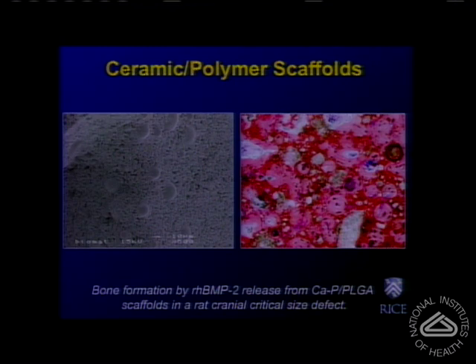And here you can see a scanning electron micrograph of this composite. The continuous phase is calcium phosphate. What we have dispersed here is biodegradable polymer microparticles. The polymer microparticles can serve as carriers in this particular case for the controlled release of an osteogenic factor such as bone morphogenetic protein 2, but also these biodegradable polymer microparticles can serve as porogens to generate porosity after their degradation to allow for the growth of a new tissue.